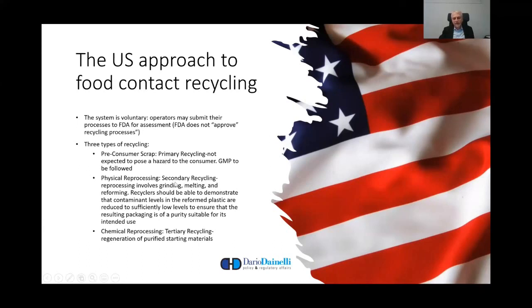The so-called physical reprocessing, which corresponds to secondary recycling, which is the one dealing with mechanical recycling, grinding, melting, reforming. And this also has to be demonstrated as safe by means of a challenge test. And third is the chemical reprocessing or tertiary recycling, which is a regeneration of purified starting materials, also considered of no concern. So eventually, the system of letter of no objection in the US is only dealing with physical reprocessing or secondary recycling.